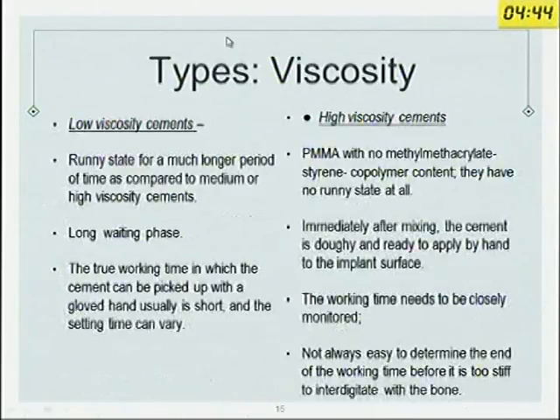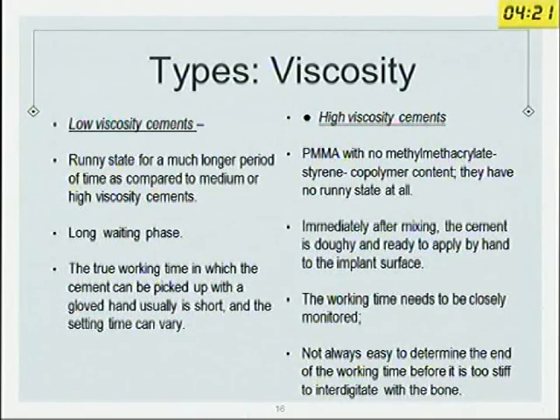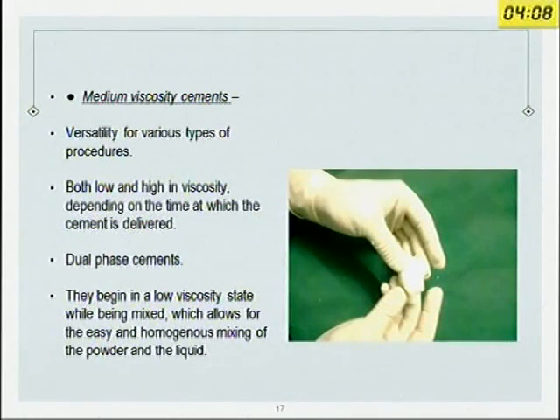It is essential to know the viscosity of the cement you are using to know how to handle it in the working phase. It has to be low enough to push into the femoral cavity, yet high enough to resist back-bleeding from the bone. Low viscosity cements have a longer waiting phase and a rather short true working time. High viscosity cement is practically ready for implantation almost immediately after mixing. Medium viscosity, as the name suggests, has intermediate viscosity — beginning in a low viscosity state during mixing, allowing easy and homogenous mixing of the two components.